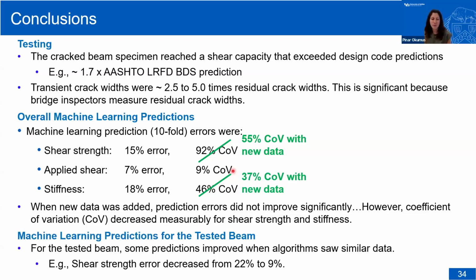Okay, and then the final conclusion is on that one tested beam. Like I said, we're retraining the algorithm using the strong side data and testing it using the weak side data. So for that one beam, some of our predictions did improve when the algorithm saw similar data. For example, shear strength error decreased from 22% to 9%. We also made our applied shear predictions better, but it didn't really help the stiffness predictions much. And again, stiffness has that issue of lack of data.